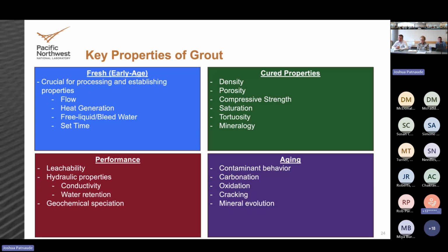In terms of performance, this is where the disposal site most heavily dictates what we shoot for in terms of properties. Leachability is a prime concern for doing waste immobilization. You're trying to isolate a contaminant or radionuclide, whether it's in a nuclear application or a wastewater application. The rate at which components leach from that waste form is key. But if the disposal site does not present a pathway for those contaminants to re-enter the biosphere, you're usually looking at some more strict threshold type leachability items.